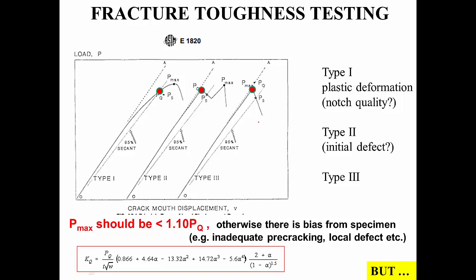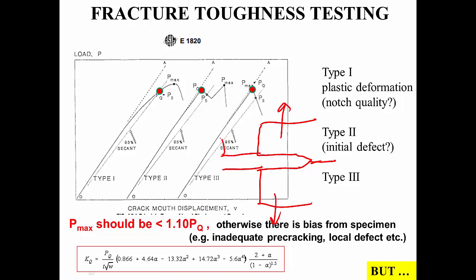Essentially, as your specimen is like this, and this is your notch, this is how you're pulling, and this is your crack that propagates there. Essentially we have a clip gauge that is mounted at the entrance of that notch, and it follows how this notch opens. It is preferred over the crosshead displacement, which is often altered by things like the compliance of the whole system, and it can create some issues.